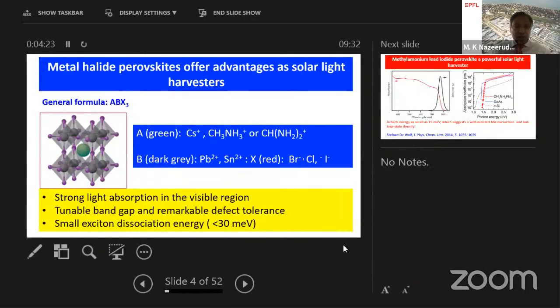So all this is happening by solution processing. But at the end of the day, you want to know what perovskite actually is. Perovskite is a very big family of materials, having the oxide perovskites and then the absorbing perovskites. The one category which we will be discussing today is ABX3. A is a monocation, which can be inorganic cesium or methylammonium or formamidinium as shown here. And we have a B cation, that's lead or tin, and halides are bromide, chloride, or iodide. So this is the ABX3 type of perovskite.